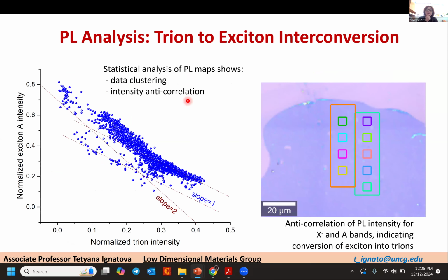Yeah. What we did, statistical analysis of photoluminescence maps, and what we see, we definitely see data clustering, and we see intensity anti-correlation between trion and A exciton. And this allows us to make the conclusion that it is a conversion of trion to exciton upon laser illumination, upon introduction of certain power. And we can even extract certain slopes because we illuminated over a certain period of time and extracted the information about the optical response of the material.